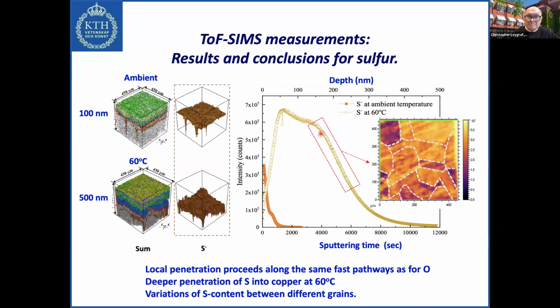Again, if we go to this immediately, the result at ambient temperature is here. The result at 60 degrees is here. The ingress, the penetration of sulfur, is even more pronounced than for oxygen. And again, there is a deeper penetration of sulfur into copper at 60 degrees than at ambient. And also, like for oxygen, a variation of sulfur content between different grains. So the results really show that oxygen and sulfur go deeper into the material.